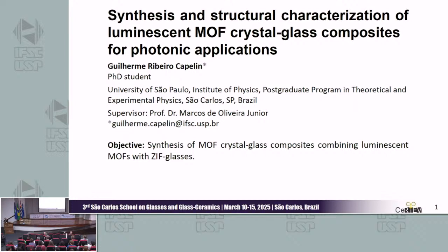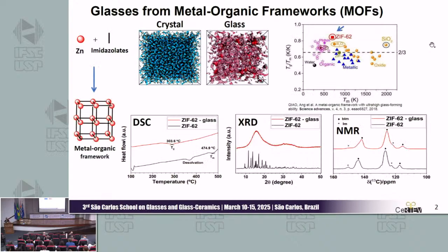So, hello everyone. I'm Guilherme Ribeiro Capelin, a PhD student at IFSC USP under the supervision of Professor Marcos de Oliveira Jr. The objective of my research is the synthesis of MOF crystal-glass composites combining luminescent MOFs with ZIF glasses. MOFs are 3D crystalline structures with organic linkers that can form porous glasses, introducing a new category of glasses. One example is ZIF-62, which has the very high glass forming ability ever reported.